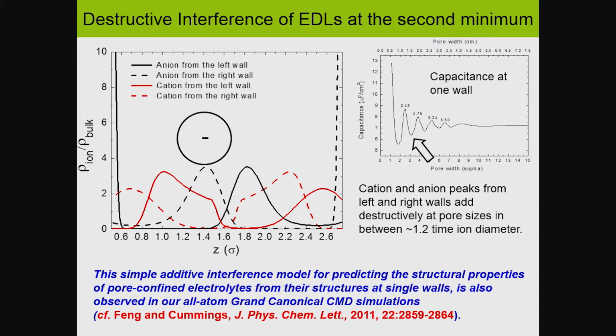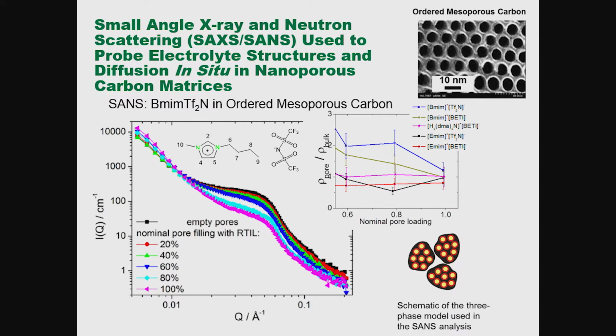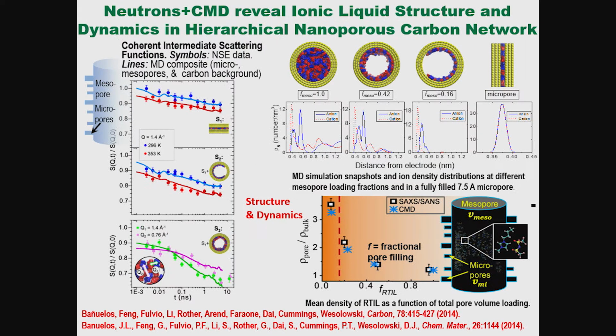With neutrons, we can look directly into pores. This is an ordered mesoporous carbon. There's a strong neutron scattering contrast between the carbon septa and the holes, which gives rise to this black curve. That bump corresponds to the pore distribution of the empty pores, and then we can selectively fill those pores with an ionic liquid and see the drop in scattering intensity, which we use to extract the density of that fluid in the pores.